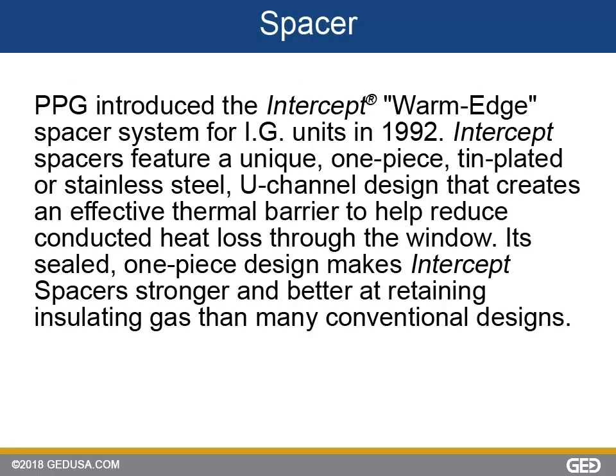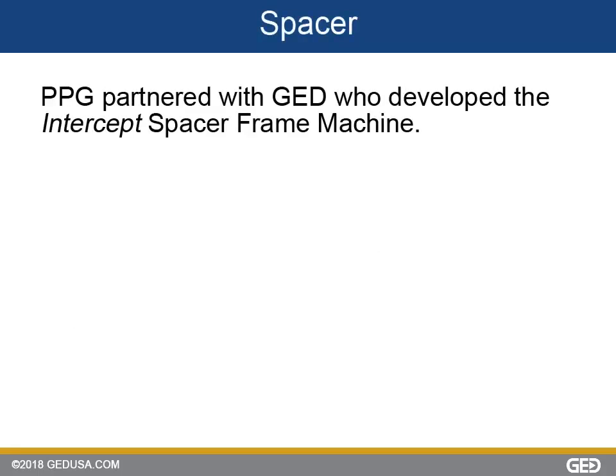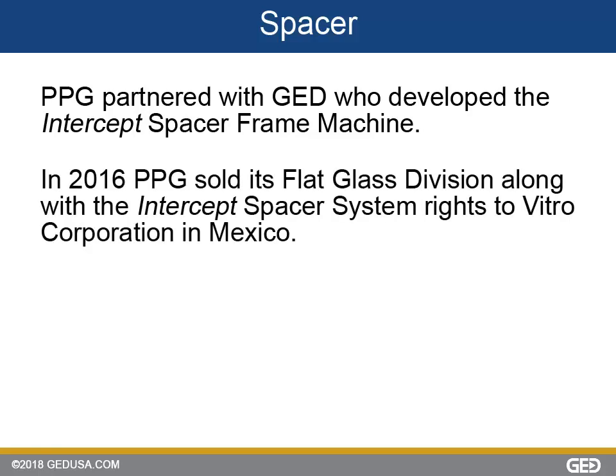PPG introduced the Intercept warm edge spacer system for IG units in 1992. Intercept spacers feature a unique, one-piece, tin-plated or stainless steel U-channel design that creates an effective thermal barrier to help reduce conducted heat loss through the window. Its sealed one-piece design makes Intercept spacers stronger and better at retaining insulating gas than many conventional designs. PPG partnered with GED, who developed the Intercept spacer frame machine. In 2016, PPG sold its flat glass division along with the Intercept rights to Vitro Corporation in Mexico.